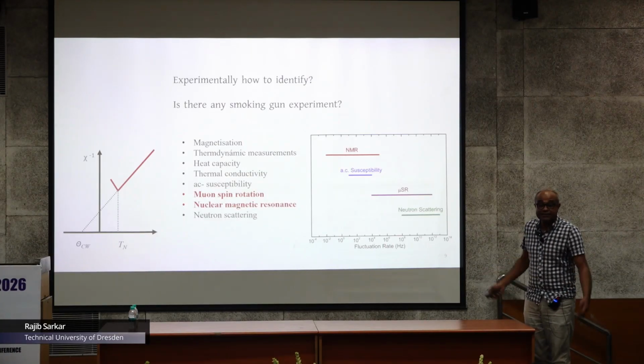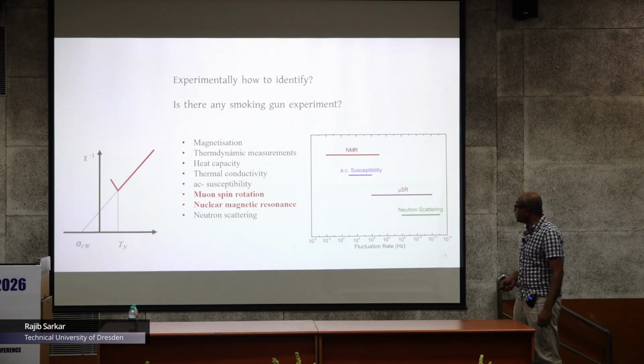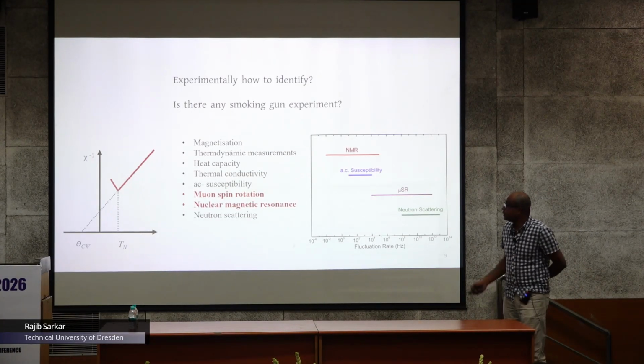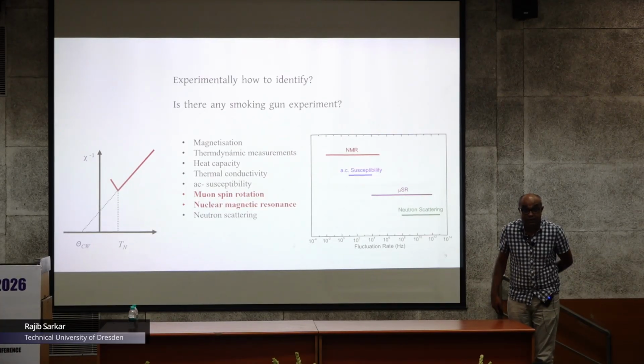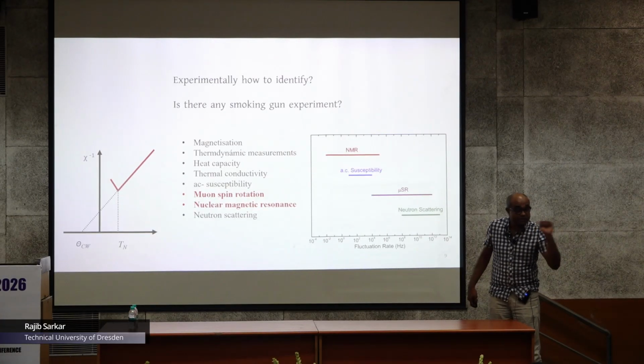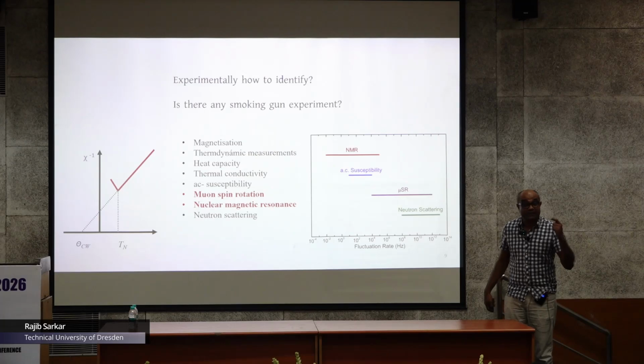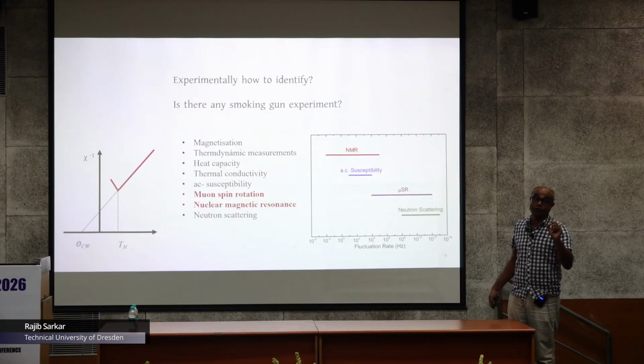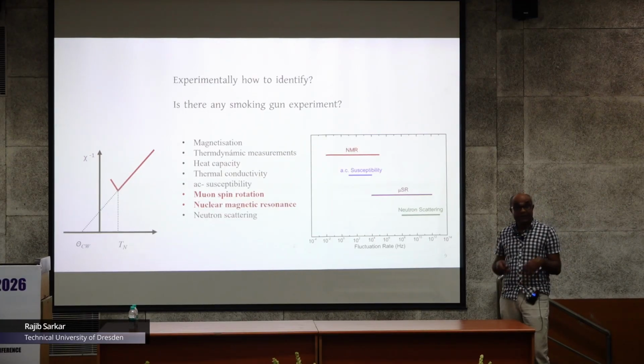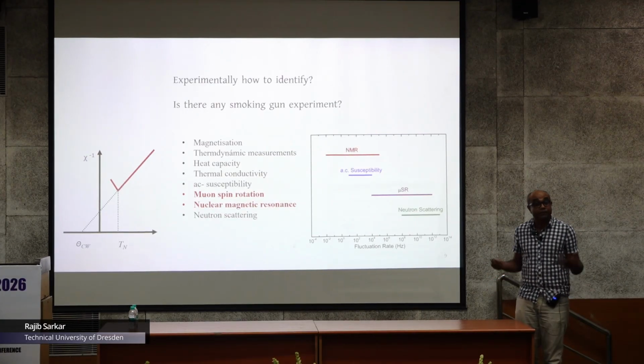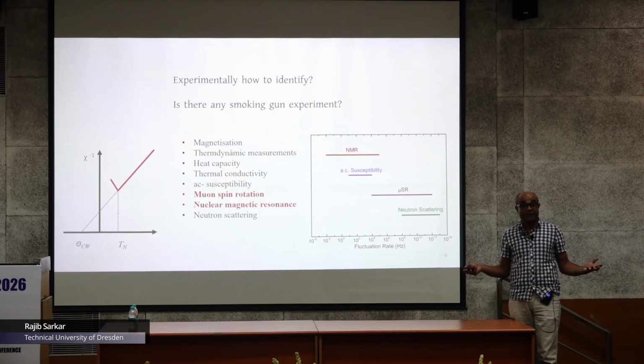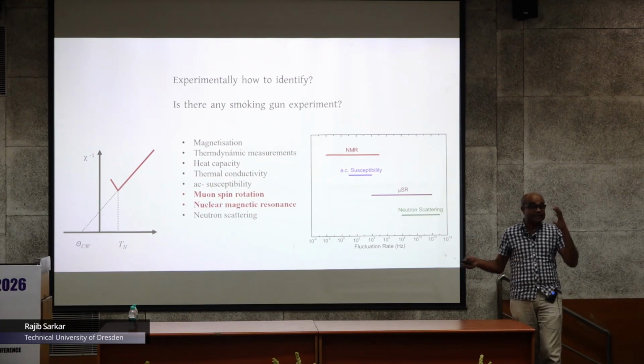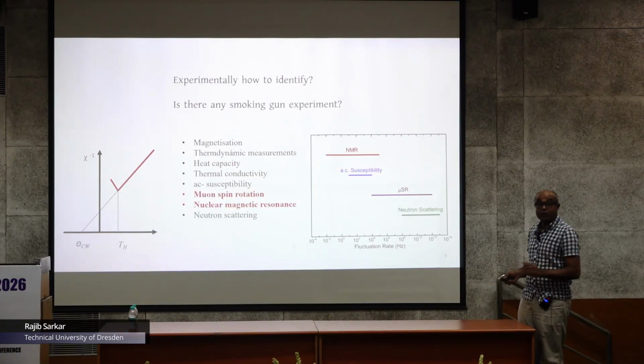And then of course AC susceptibility, and then microscopic probes like muon spin rotation and nuclear magnetic resonance. These two techniques, as Shushanto Dattagupta was asking, can track the very low energy scales, a fraction of a micro electron volt only. Now if you go a little bit higher in energy, which is neutron scattering, of course there you can see the momentum space, right? So that means Q dependence you can measure there. Therefore all the excitations or other things you can track by neutron scattering.